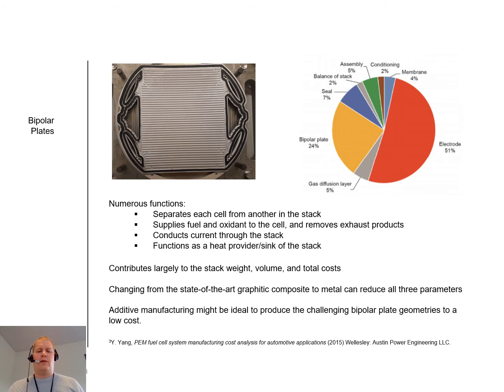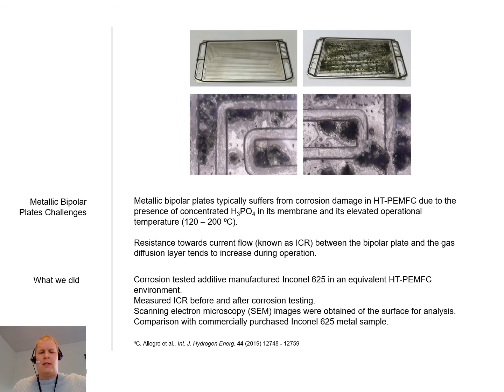Changing from the state-of-the-art graphitic composite material to metal can reduce all three of these parameters, and using additive manufacturing might lower the cost due to its potential of producing challenging geometries. The challenge of using metallic bipolar plates is corrosion. In a high-temperature PEM fuel cell, there is a presence of concentrated phosphoric acid in its membrane, and in combination with an operational temperature of 120 to 200 degrees C it creates a highly corrosive environment.